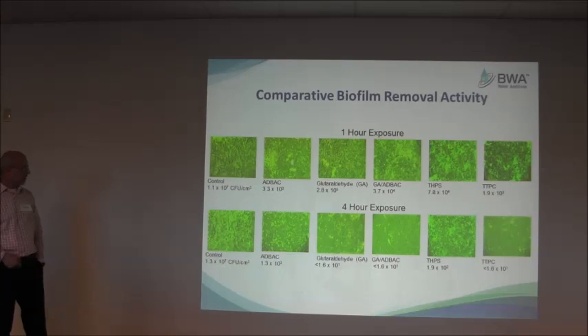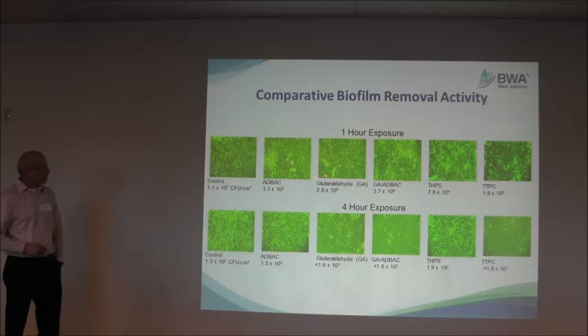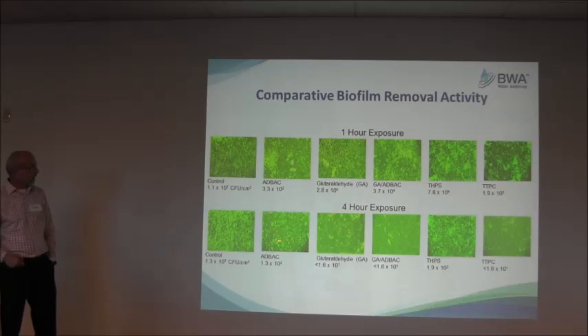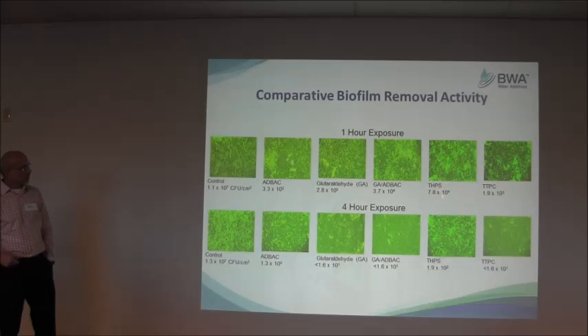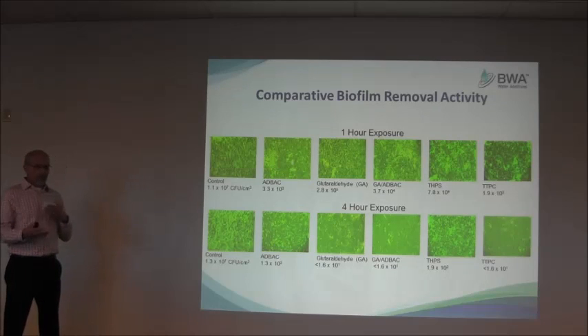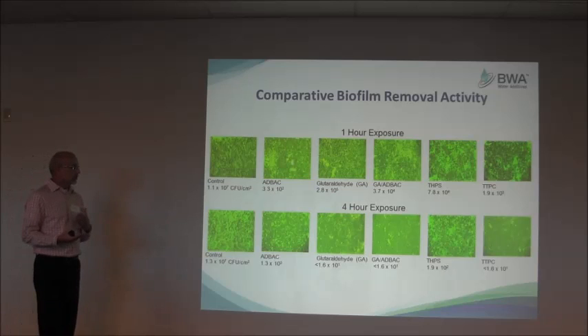We also have high viability at 10⁷ in both control timepoints. As you go across, you can see that different biocides have different biofilm removal effects. After one hour, there's not much removal compared to the control. TTPC is showing some of the best removal. After four hours, you can see more removal going on. THPS really doesn't improve its biofilm removal from one hour to four hours, while TTPC looks quite good, with removal similar to the viability plot.